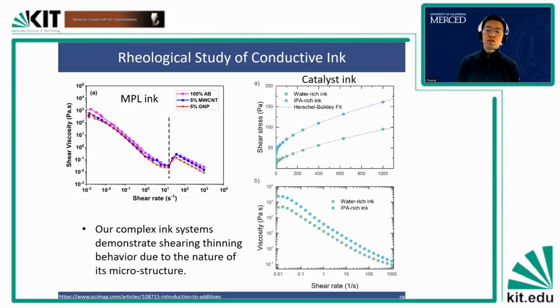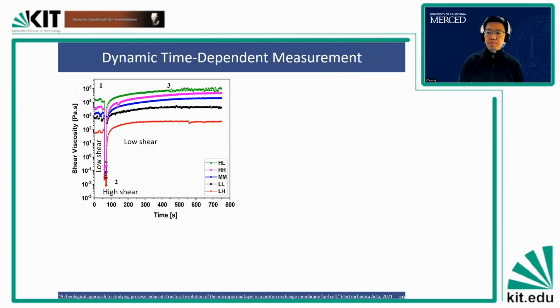But in order to understand this a little bit more in terms of microstructure, we also study this dynamic measurement. And within this dynamic measurement, we have different shear steps. So three steps, which is called three-phase rebuild. The first step is low shear. Then you shear them at a very high shear rate. You know the viscosity will drop. And then after that, we let the viscosity recover itself to understand the time-dependent behavior.